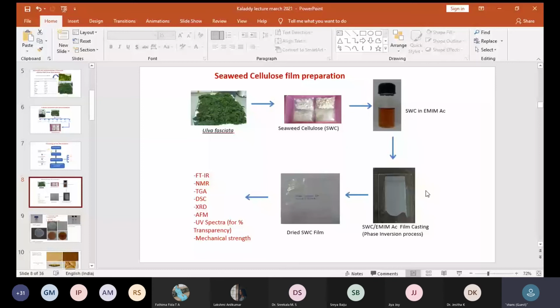In addition to that, we also converted the cellulose to a carboxyl derivative. We did the carboxylation reaction and tried to convert the OH group into COOH. That means water insoluble cellulose can be converted into a soluble form of compound, that is carboxylated cellulose, which we call seaweed carboxymethylated cellulose.